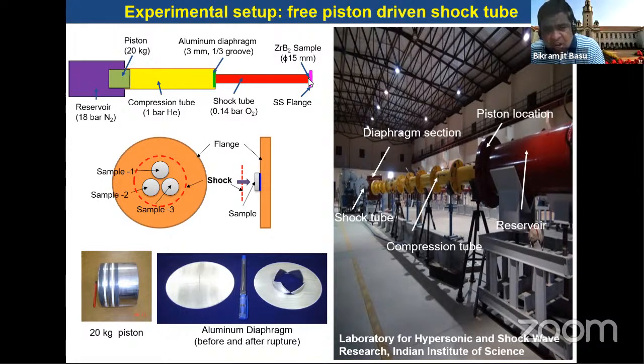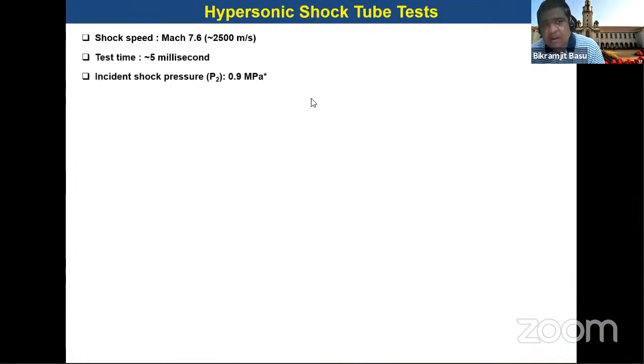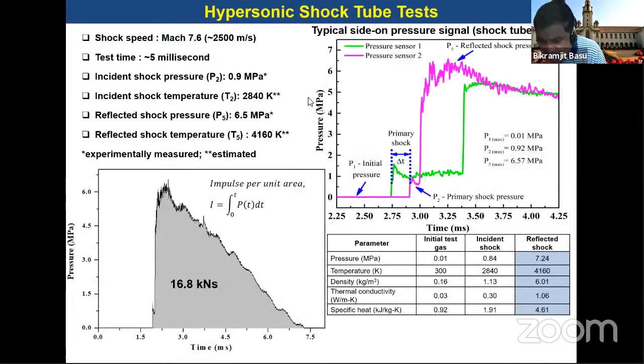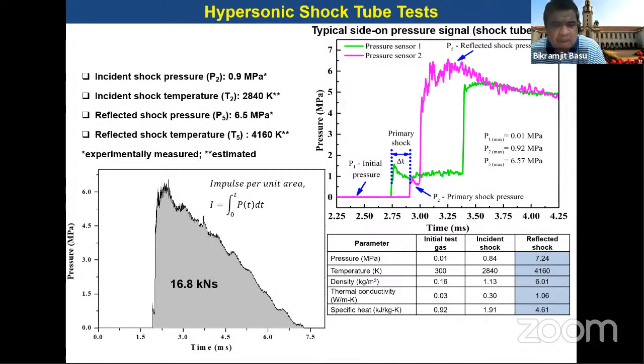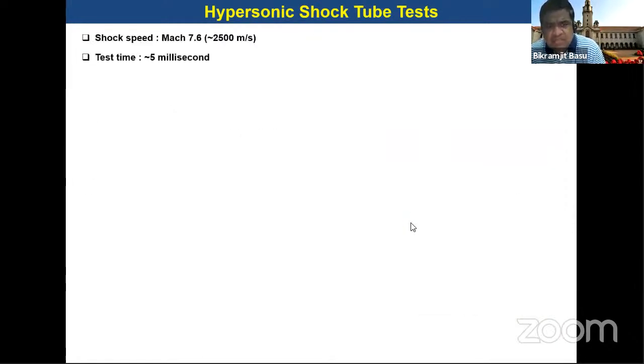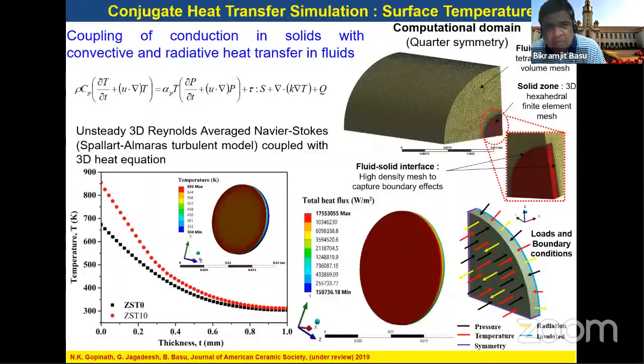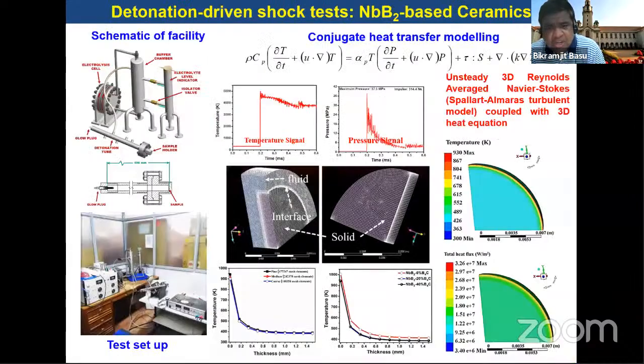By putting in different pressure gauges, you can monitor the pressure being generated in this shock tube, and then you can calculate the expected temperature increase by certain theoretical calculations. Now, this is the typical pressure pulse this material is experiencing over a period of a few milliseconds. And this is what we have calculated: the initial test gas pressure and the incident shock gas pressure. From there, we can find out that the reflected shock temperature is over 4000 Kelvin. That is very important to keep in mind. But remember, this material is experiencing this kind of shock pressure over a time scale of a few milliseconds, less than 5 milliseconds.